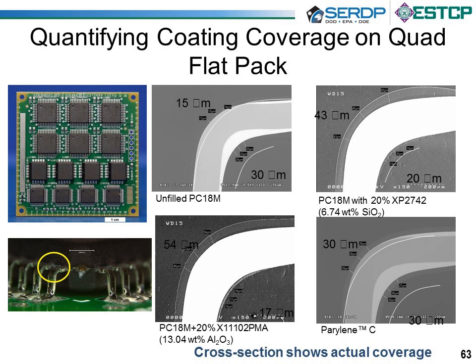To help support the modeling, there was a need to quantify the coating coverage. And so we utilized a quad flatpack. This one happened to be a 44-pin. We also included a thinner one, a 64-pin, and a plastic leaded chip carrier, different lead configurations. But we settled on the QFP44 to do our thickness characterization, with a cross-section down the middle of the lead.